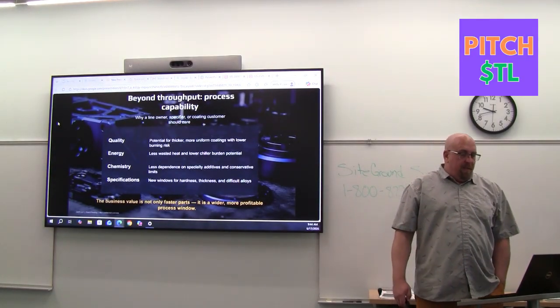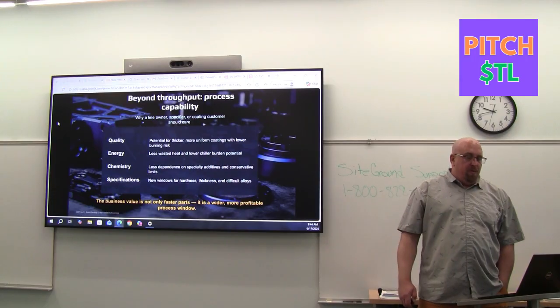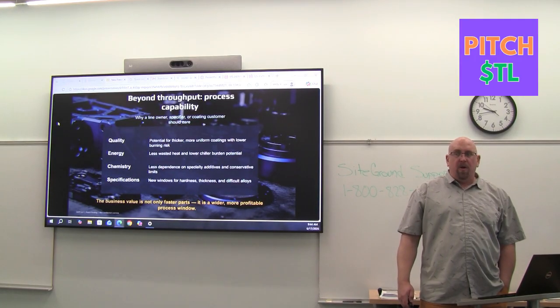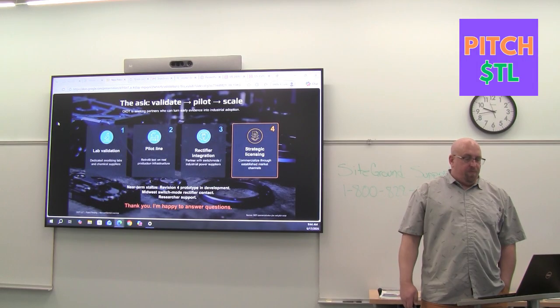For the line owner, this impact goes beyond throughput. More coating per unit time is the headline, but the broader value is a larger operating envelope. They can reduce heat and chiller burden, have less dependence on specialty additives, lower their energy costs, and meet difficult specifications for hardness, thickness, and alloy performance. This technology is disruptive in the best sense of the term, as it does not ask the industry to throw away what already works. It instead helps the industry get more from what it already owns.